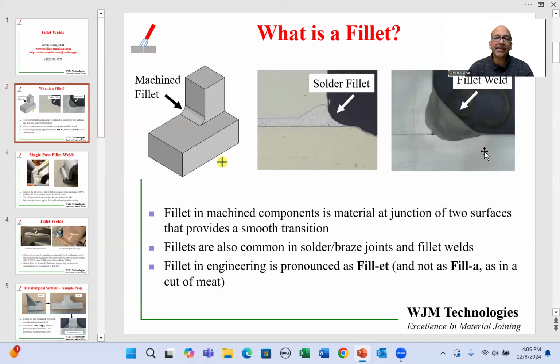On the right, we can see a cross-section of a fillet weld, where we can see the fillet which has been deposited by adding wire in this particular case. And the dark colored zone is the material which actually melted during the weld and formed that fillet.